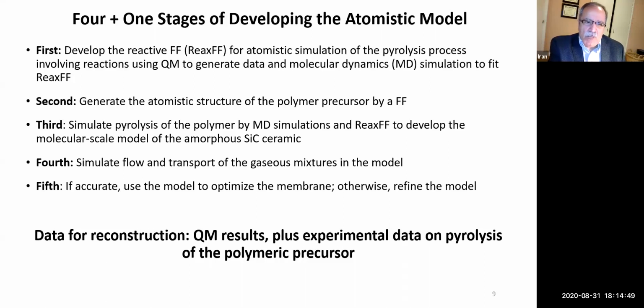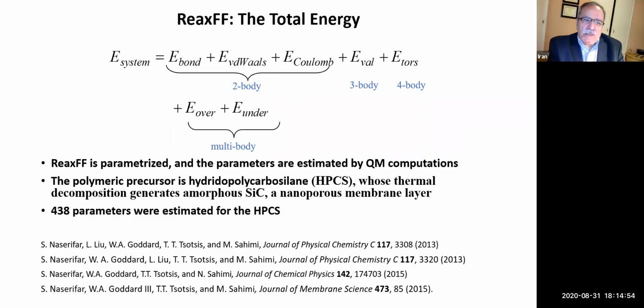structure of the membrane. Just to explain how it is done in any force field, you express the total energy of the system as a sum of many energies. Any configuration in the molecular structure that costs energy to deform, stretch, or compress, for example, has a term here. For example, a bond can be a stretch, so that's the first term, E bond. There are van der Waals forces, two-body interactions, that's the second one. A lot of molecules are charged, and therefore there are Coulombic interactions, that's the third one. You can have two bonds that are connected to each other, and two bonds can deform with each other. So that's the three-body term that you see. You can have four bonds, three, let's say, in one plane and one perpendicular. That's another one. And then you have multi-bond, an atom interacts with many of them. Sometimes the valence is less than what it should be, sometimes it's more than what it should be, and so you have to account for that.